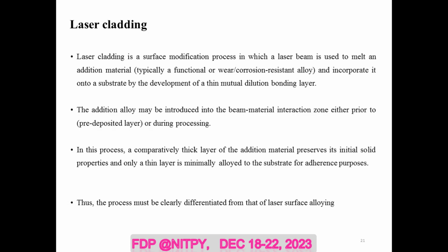The alloy powders will be penetrated and intermixed with the substrate material. But in laser cladding, the alloy powders will be deposited on the substrate material. So there is no intermixing or penetration of alloy powder into the substrate material in laser cladding. So these are the major differences between laser alloying and laser cladding.